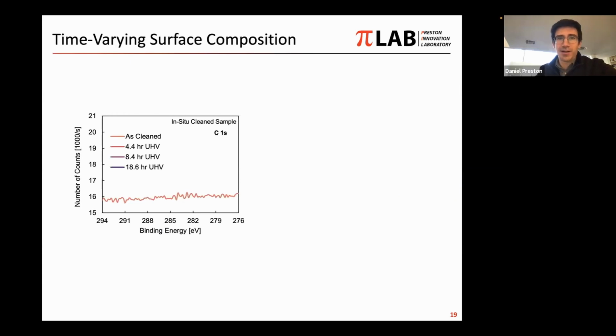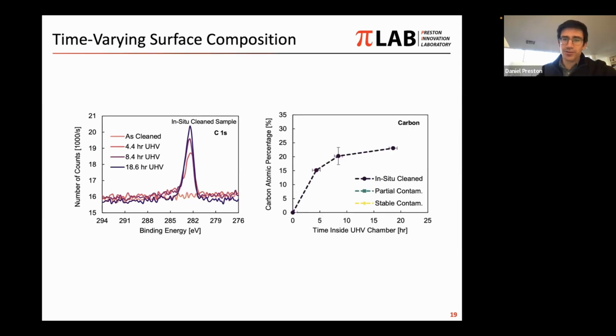We looked at this time varying surface composition. So this is the in situ cleaned sample that was sputtered with the ion gun in the XPS chamber. And over time, 4, 8, and 18 hours, we see an increase in this carbon peak measured with the XPS instrument. And so that's shown here in the plot on the right. We get an increase in the carbon atomic percentage that we can calculate from the XPS as a function of time in the chamber.